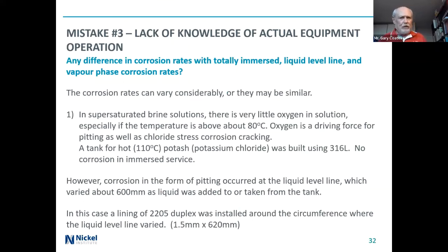We also have to think about differences in corrosion rates in the immersed condition of the material, right at the liquid level line, or in the vapor phase, and they can vary considerably, or they could actually be similar depending on the environment. So for the one case I take here, a supersaturated brine solution, this is with potash, potassium chloride solution. In supersaturated brine solution, there's very little oxygen in the solution, especially if the temperature is above 80 degrees C. Oxygen is, of course, a driving force for pitting as well as chloride stress corrosion cracking.